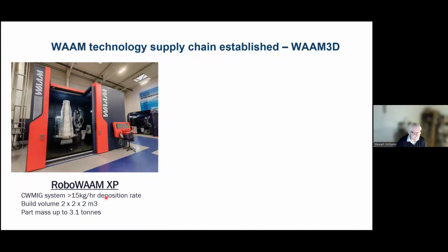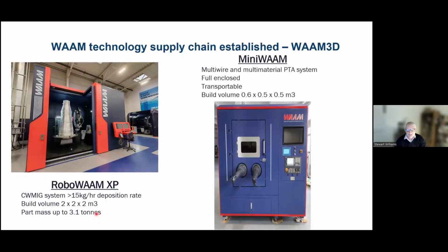And this system is based on a much higher deposition rate process. So with this system, we're depositing 15 kilograms per hour, and we can build parts up to 3.1 tons. And then at the other end of the scale, we have what we call a mini WAAM. It's not so mini actually. The build volume is 0.6 by 0.5 by 0.5, but it's transportable, fully enclosed, and it's primarily focused on materials development and research. So it has multi-wire and multi-material capabilities.